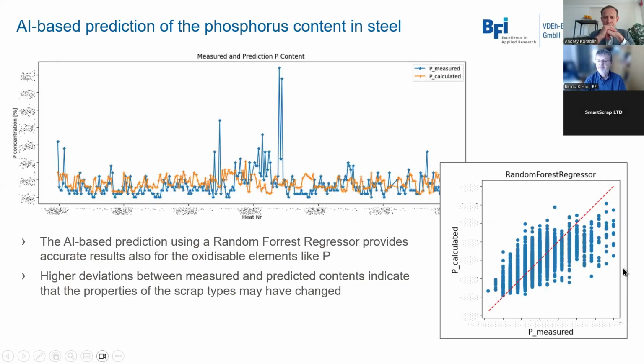Okay, so then we have a prediction of the phosphorus content by means of this AI-based model. So we can compare the calculated value to the measured one. We can see that now the accuracy has improved a lot compared to the multilinear regression model. And we can now use this AI-based model to predict the phosphorus content at the end of the treatment for each heat. And you can see here comparison between the measured values in blue and the calculated values in orange.